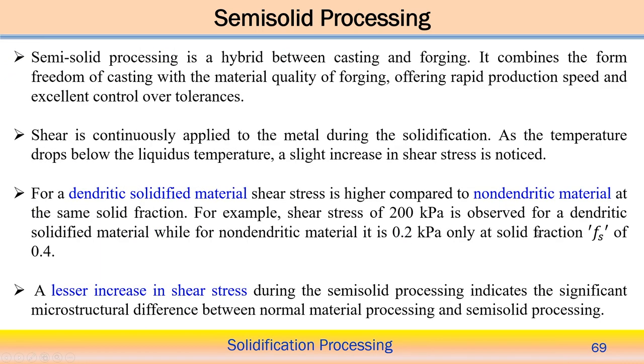Now, we can represent semi-solid processing as a kind of hybrid process between the casting and the forming or forging process. It combines the freedom of form of casting, because in the casting process, once solidification is allowed to take place, there might be some homogeneous and heterogeneous nucleation, and gradually the nuclei form and try to grow, and then we can expect a certain specific structure or microstructure for a cast component after solidification.